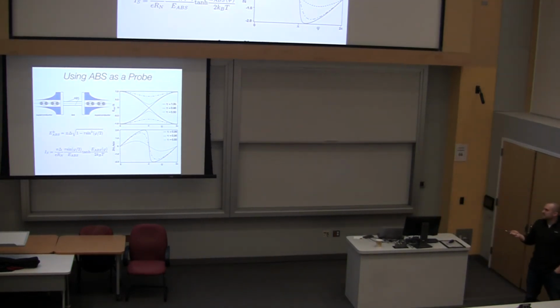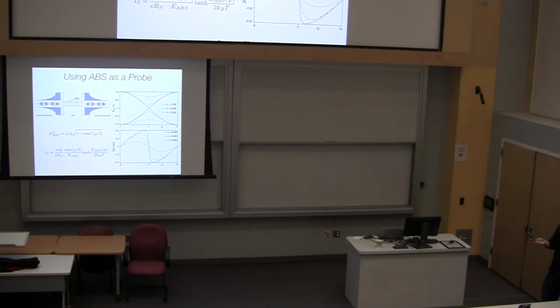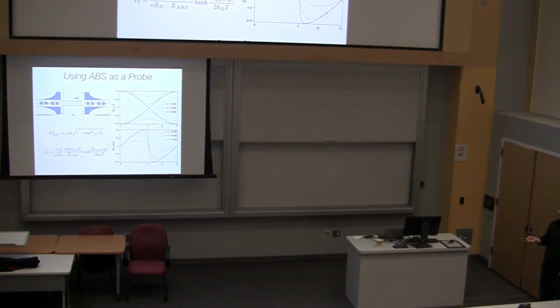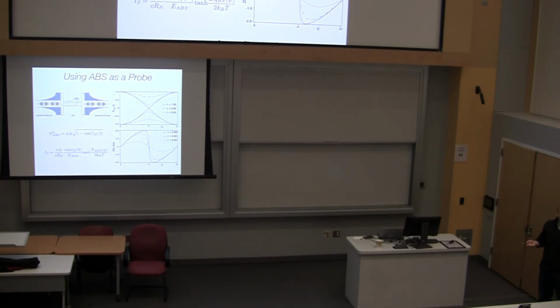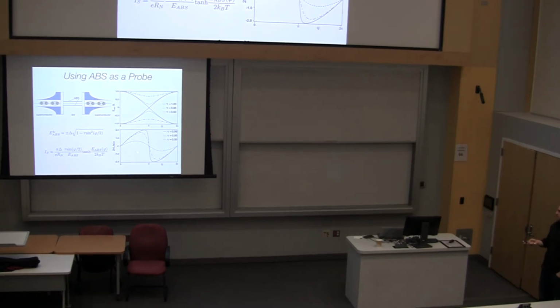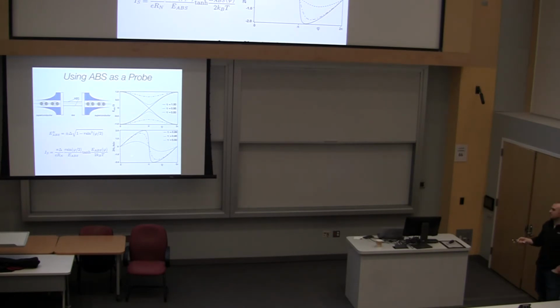So you can see the effect of changing the transmission probability of how Cooper pairs move through these junctions, in particular how the normal state electrons move in this region. If the transmission probability is half, which is very common in devices that used to be fabricated, what you get for this current phase relationship is something very sinusoidal. But as you start to change the transmission probabilities, by either making your junction cleaner or changing the properties of the normal material that lives in between these two superconductors, you get an increasing skewness of the current phase relationship.